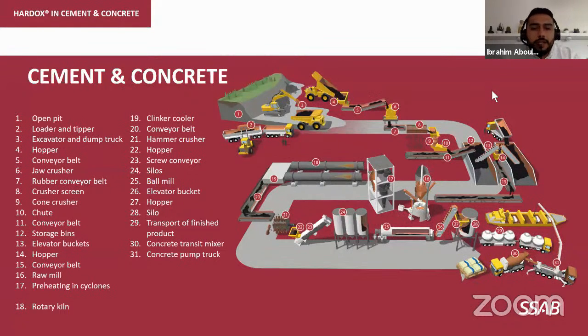After the rotary kiln, in step 19, we have the clinker cooling bed, in which the temperature drops to somewhere below 500. For that we have a specific solution called Hardox HiTemp. Quenched and tempered plates like Hardox, when heated above a certain temperature, experience something called softening. If you have a Hardox 600 and you raise the temperature of the plate higher than 220 degrees, it will start to back temper and lose its hardness until it reaches maybe 300 Brinell, which means you buy a Hardox 600, but you get a 300 Brinell. So this is why it's not recommended to use Hardox at temperatures higher than 220 degrees.